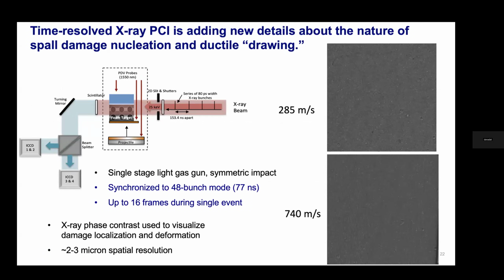So the overall sample size is, so the gun there, we're using basically a half-inch bore. So the sample itself and the impactor are half-inch diameter. And then what we're doing is only looking at a very small portion in the center of the sample. And actually, we do wave code calculations, and we have to position the sample, you basically have to do a transition between Eulerian and Lagrangian coordinates to make sure that you can catch the image, because the damage plane essentially moves through your field of view during the experiment because it's moving at the particle velocity of the material.